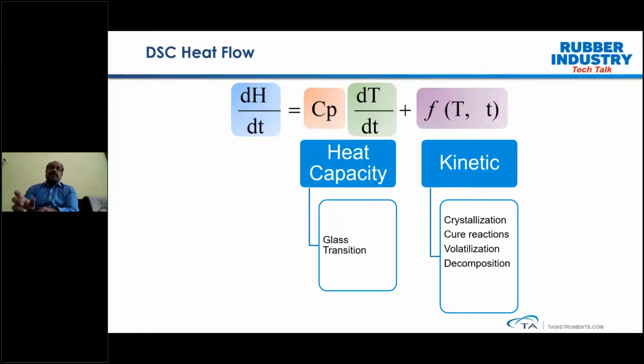The heat flow changes would happen due to two aspects. One is heat capacity changes and the other is kinetics. The heat capacity change is usually, for example, as the sample undergoes the glass transition temperature. So what is happening is your heat capacity is going to change before and after the glass transition temperature.